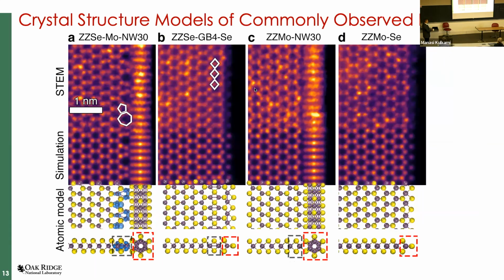We of course like to take these STEM images. So we've commonly seen 4 different types of reconstructions, zigzag terminated. So you have a zigzag orientation here, selenium atom right here. You have a single moly atom, and then this little nanowire that starts to form. Why I'm showing this and why this is so important is because STEM images can provide you only so much. Again, the beauty is marrying the STEM imaging with the theory to understand a little bit better.